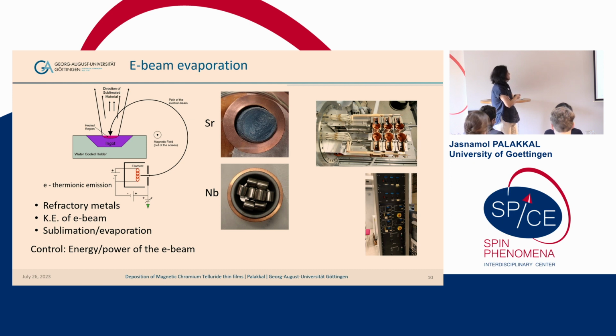So in this case, you are heating a filament, and due to thermionic emission, you get a lot of electrons here, and these electrons will be deflected and directed to the source by using deflecting magnets, and this will evaporate this material, and finally you get the vapor of this material. And in the case of an effusion cell, you were controlling the rate of evaporation by using temperature, but in this case you are controlling it by using the energy of the electron beam.